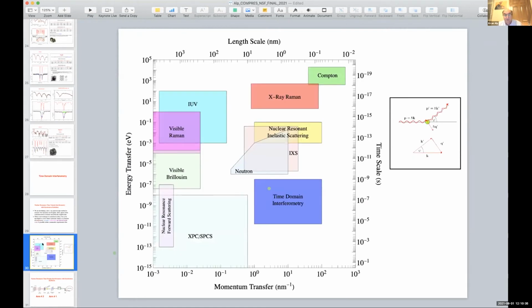So what is it that we're developing? This figure is a loaded figure, and the physicists love it. And everybody else is sort of like, well, so if you look at the energy transfer range, we're talking about 20 orders of magnitude from 10 to the minus 15 to 10 to the 5 eV. So Compton scattering, for example, with the keV energy transfers at hundreds of keV is an extreme case where you can separate conduction electrons from the core electrons.